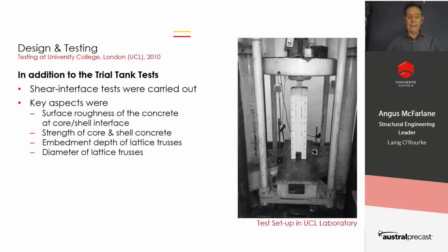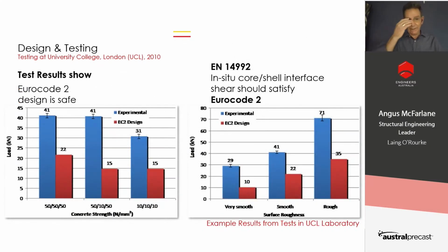Now, design and testing, as I mentioned earlier with the Beckton treatment works, the trial wall, there's a lot of testing done at University College London, UCL. Mainly the testing was a shear interface test to check that we could actually get composite action. The key aspects of those tests are the roughness of the concrete, the strength of the core and the strength of the shell concrete, the embedment depth of the lattice trusses, and the diameter of the lattice trusses. So those were all the variables that were used. There were hundreds of tests carried out, and I just show a summary of a couple of tests.